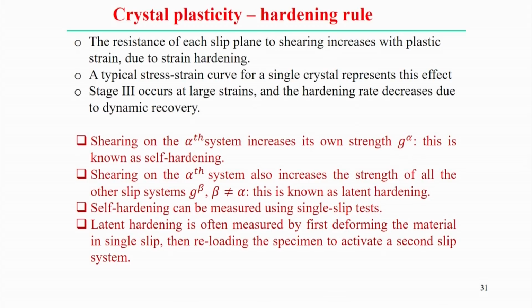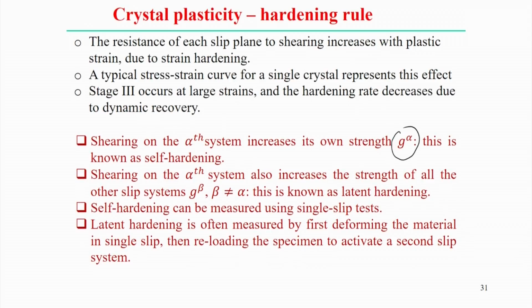Now, how to use the hardening rule in a single crystal plasticity model. The first thing is that we consider the shearing on the alpha system increases its own strength, probably defined by G alpha, and this is known as self hardening. Self hardening means the increment of the strength level due to a specified shearing operation on a slip system, but at the same time this slip system can also affect the deformation behavior of the other slip systems. So in the second case the shearing on the one specified slip system, alpha, also increases the strength of all other slip systems, represented by G beta, where beta is not equal to alpha, and this type of hardening is known as latent hardening.